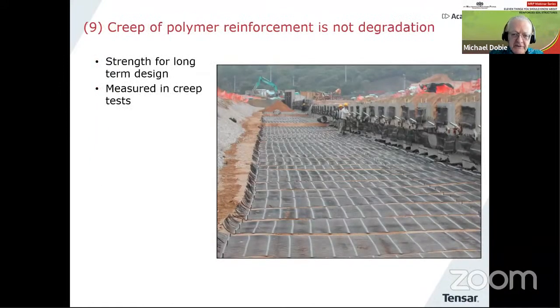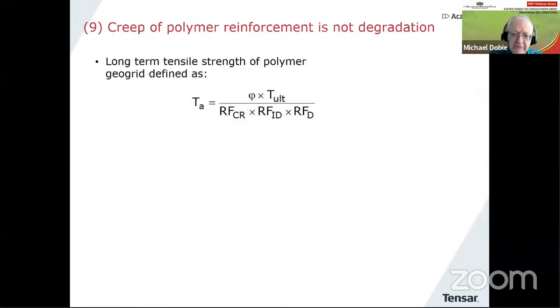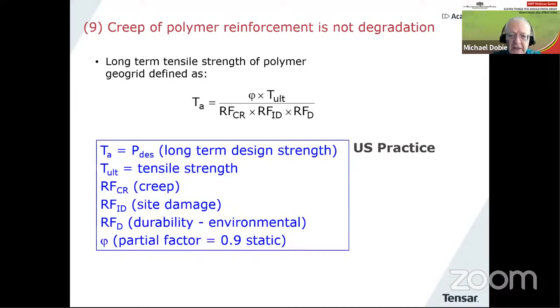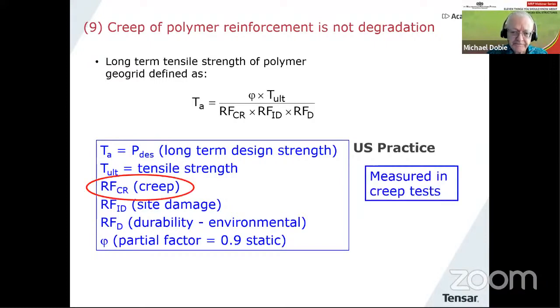So here are some, in this case, HDPE geogrids laid out on the site behind a retaining wall facing. And to determine their long-term properties, we carry out what are called creep tests. And then we put the information combined with other reduction factors into a formula like this. This is typical US practice. We take into account creep, site damage, and environmental effects like chemical and oxidation. They're all going in there. And that gives us the allowable strength.